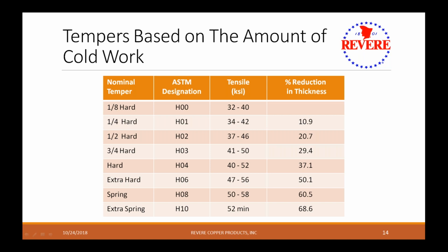So, back to my other example where I did a 50% reduction, that would be extra hard on this chart. So if you look at extra hard, and you went from a 1/2 inch and you rolled it to a 1/4 inch, you would have a 50% reduction, and your tensile strength would be 47 to 56, and it would be designated as extra hard, or H06. And this chart kind of shows you all the different options that you can order metal through, and this is the ASTM standard.